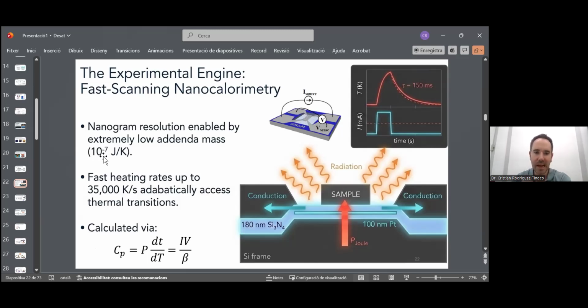But since the addenda, the heat capacity of this device, is very small, it can heat up very fast, even with this small amount of power. Fast means like 10 to the 4, 10 to the 5 Kelvin per second. Typically, we work at a heating rate of 35,000 Kelvin per second. So fast that we can consider this measurement as quasi-adiabatic.